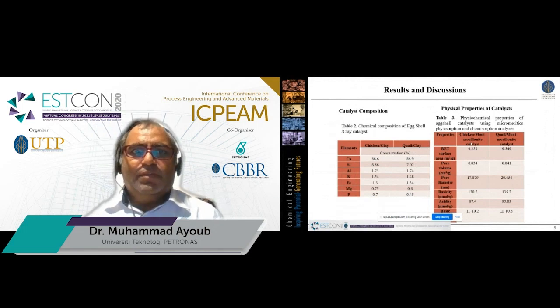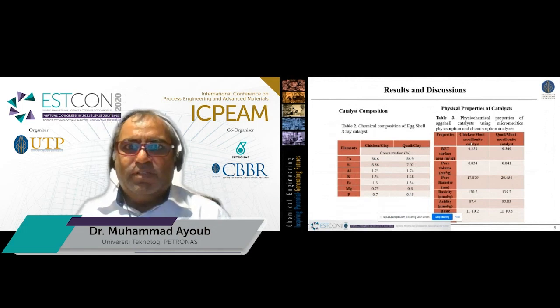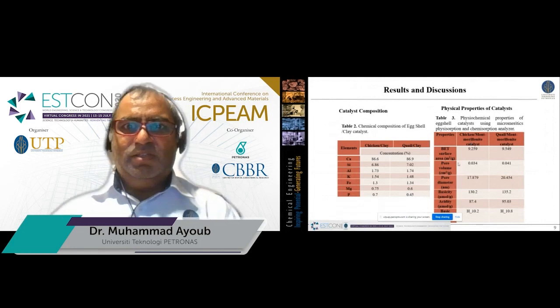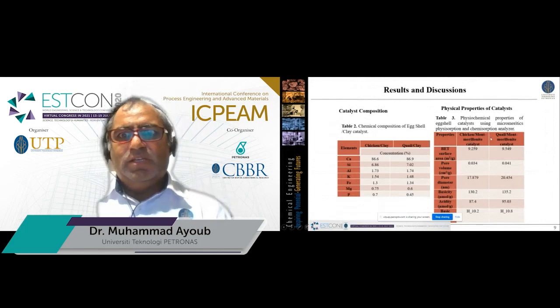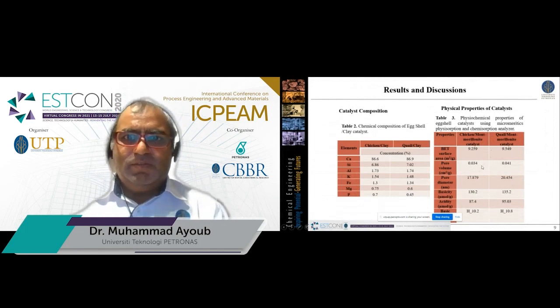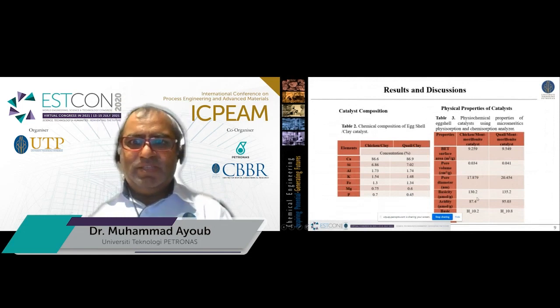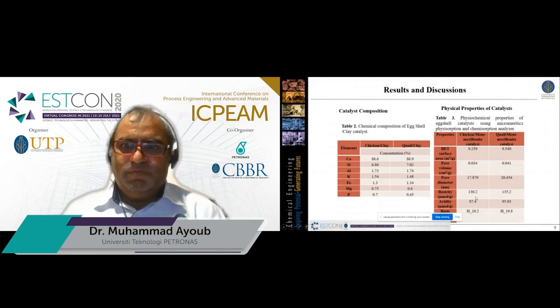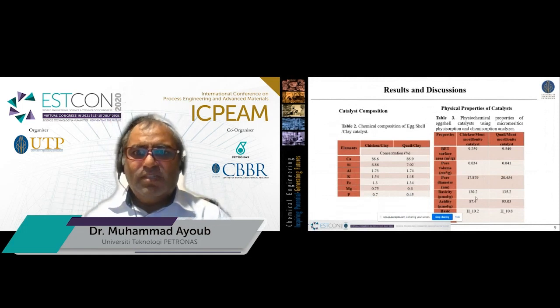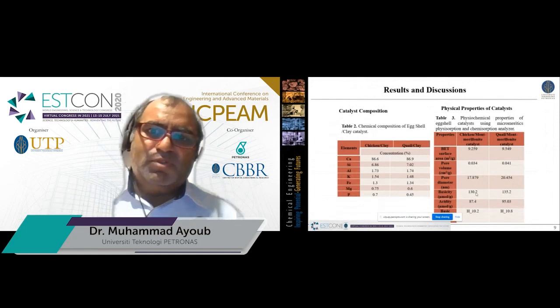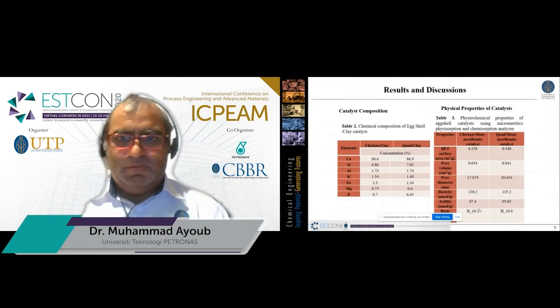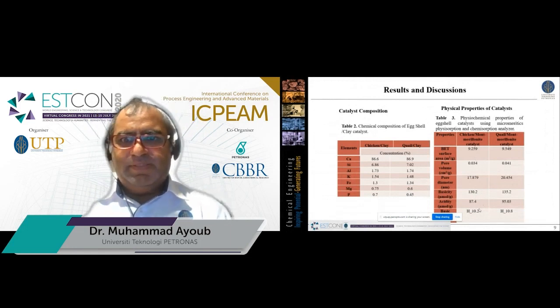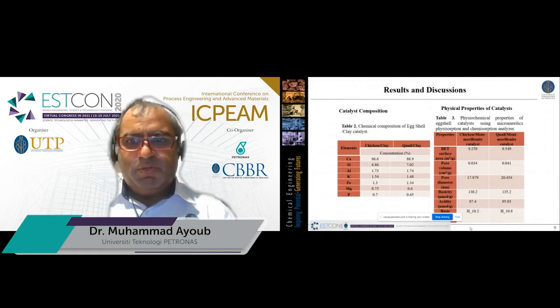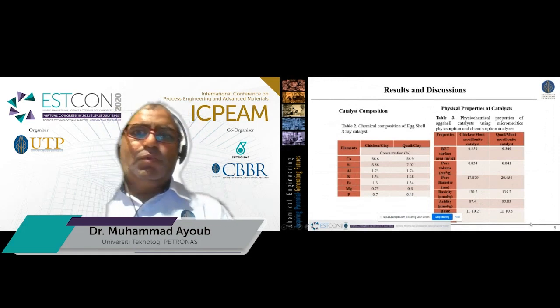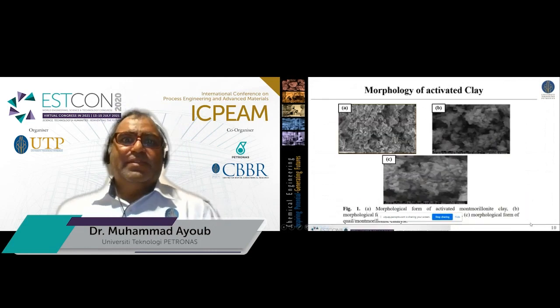We also measured physical properties of the catalyst, such as BET surface area. You can see that chicken and quail have close surface area, 9.25, and similar pore volume and pore diameter. Basicity is very good, and both have the same. Acidity is low, because it is mostly in the form of calcium. Therefore it is more towards basic. In the Hammett test, we can see it is 10.2 to 10.8. So we can say our catalyst is basic.